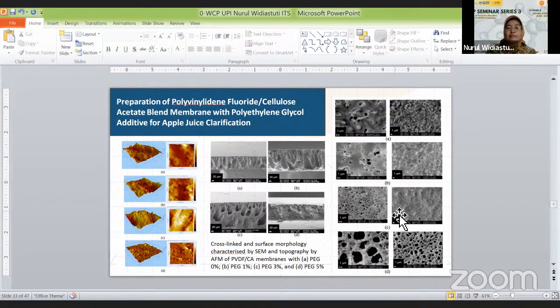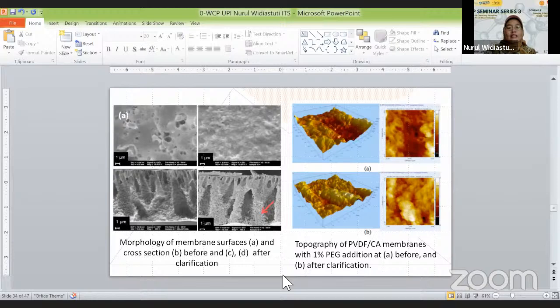They can control the pore size of the membranes to make them homogeneous and smooth over here. However, when we increase PEG up to 5%, the polyethylene glycol affects the pores of the membranes and makes a much bigger pore size. So we decided to choose the maximum amount of polyethylene glycol, which is 3%. And this is the comparison of the morphology of membrane structures before and after, and also the topography of PVDF-CA membranes with 1% PEG addition before and after also.